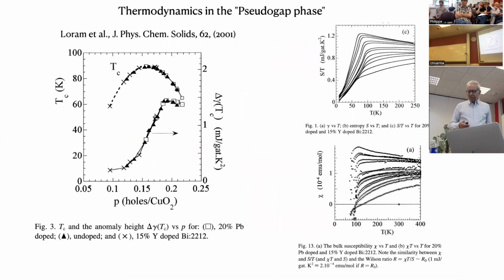Okay. I mentioned this thing about the thermodynamics. Now, I will use this thing that you've heard about, the pseudo-gap phase, which was first discovered by Henri Alloul through Knight shift measurement. So the Knight shift is supposed to be roughly a constant, but in this compound, here is a thermodynamic measurement, which is somewhat related to the Knight shift. The magnetic susceptibility was roughly a constant for dopings near that doping in that dome, and then it began to change at some temperature, and the temperature where it began to change is that line T star that I drew.